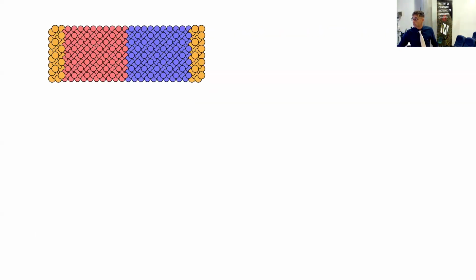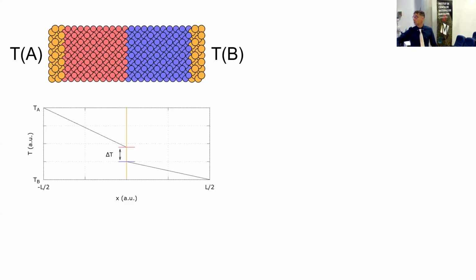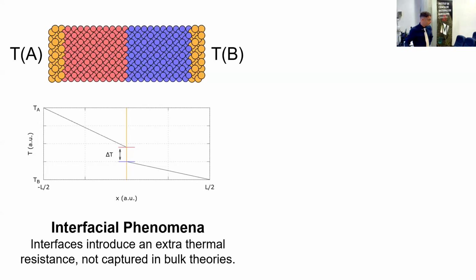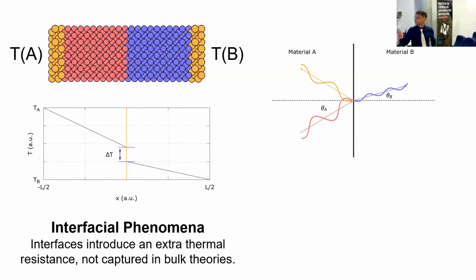Well, if you take a material like this one, a generic one, and we keep the two ends at fixed temperature, say TA and TB, with TA greater than TB, and wait for the system long enough to reach a steady state, the temperature profile will be different from the previous case. It will exhibit a pretty sharp temperature drop in the interface region. And this is an interfacial phenomenon, meaning that interfaces introduce an extra thermal resistance, which is not captured in bulk theories.